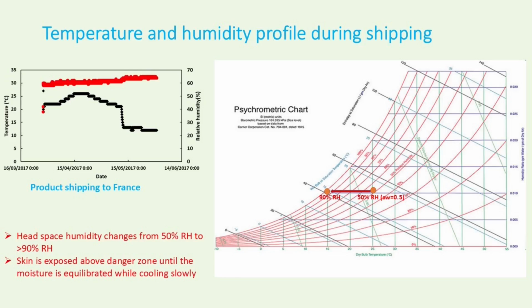When the temperature drops, the humidity actually increases, from 50% to 90%. When it goes to 90% humidity, it doesn't diffuse inside immediately. There is a diffusion of moisture inside, so it remains on the surface. When it remains on the surface, it promotes crystal growth. Even though they are very small crystals, because of the humidity on the surface, the crystals start growing fast. So that was explained very well, why it is happening.